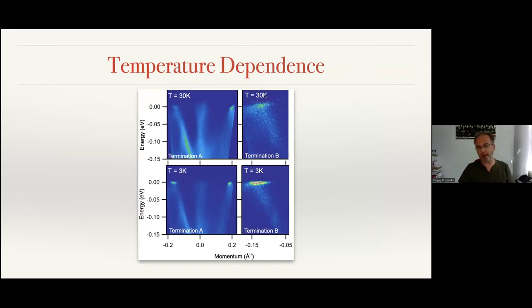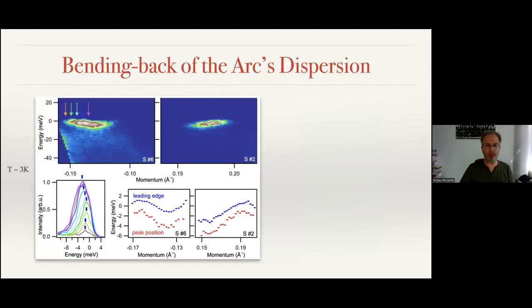And you see here that warming up the sample from 3 kelvins to 30 kelvins, this flat dispersion, this flatness and this coherence, got lost. So this is a very typical sign of superconductivity. We investigated it closer, and we found another typical sign of superconductivity. This is a zoomed-in picture of the Fermi arc. You see the energy scale here is only 14 millielectron volts, and the cuts from the vertical slice of the onion are here. And you see the typical sign of the opening of the superconducting gap.